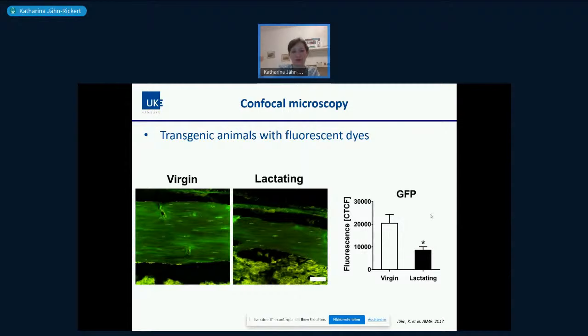So when we looked at the lactating mice, we were curious to know if the osteocytes are really using an acidic environment to resorb bone matrix around the osteocyte. We found out from the literature that the green fluorescent protein, GFP, is sensitive to an acidic environment. Therefore, fluorescence should be quenched, so lowered. We had transgenic mice expressing GFP under the collagen 3.6 kb promoter. You can see here in the virgin mice, the bone matrix is nicely green and fluorescent. And with lactation, this fluorescence was quenched.